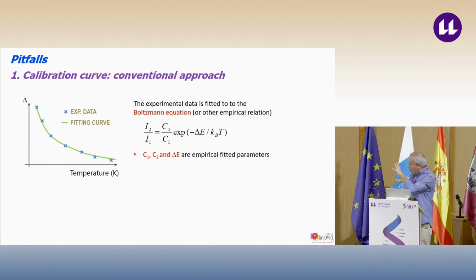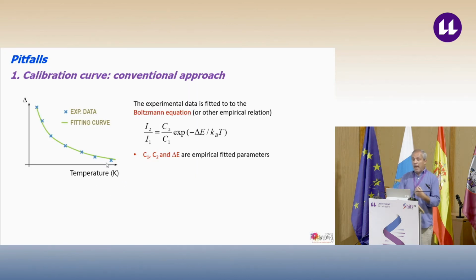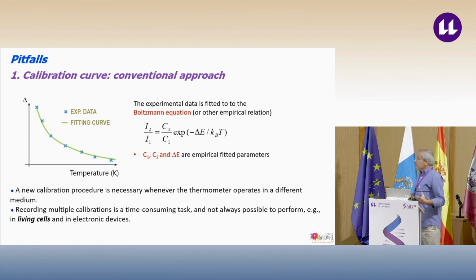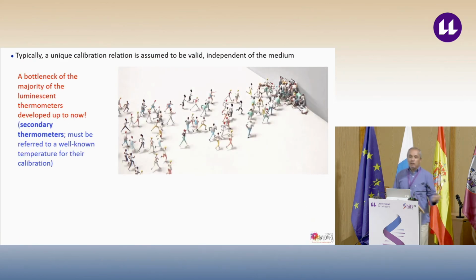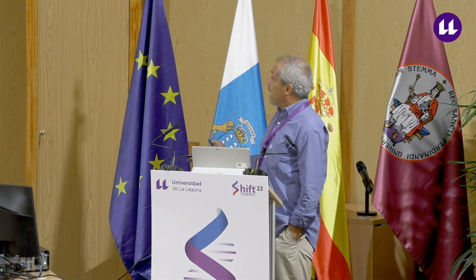What I think could be problematic is the calibration curve, as I mentioned before. So this is the conventional approach. People have experimental points, then they fit the experimental points with an empirical equation or with the Boltzmann equation, which means that when they move from one medium to the other, they need to repeat the calibration. But in an intracellular environment, this could be very, very difficult, okay? And then what typically people do is assume a unique calibration relation. And this is clearly a bottleneck.